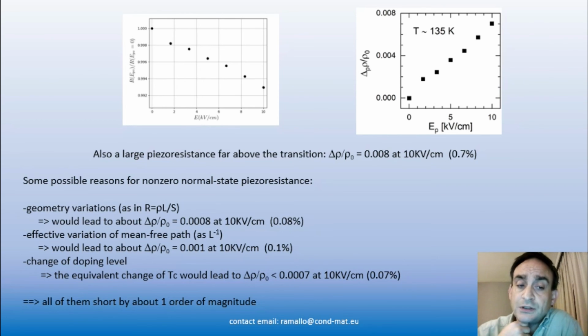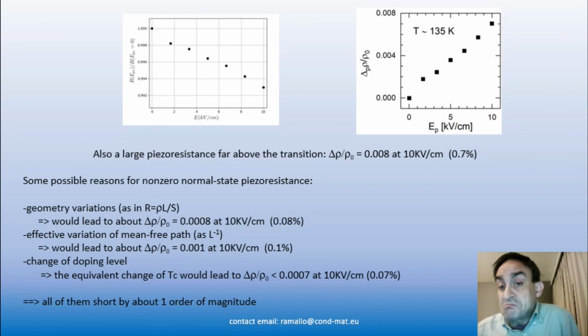It could also be an effective variation of the mean free path. It's quite similar to the size variation, but this time taking into account the mean free path. But this again is one order of magnitude smaller than what is seen. One could also think about the possibility that if you change the size of the unit cell, then maybe you are inducing a change in the doping level. But if you see how much the critical temperature changes and you translate that to a change in doping, then this also produces an effect one order of magnitude smaller than what is observed. So this is not really a very good explanation, to my knowledge, for this effect, but the fact is that it's a normal state effect that is there.